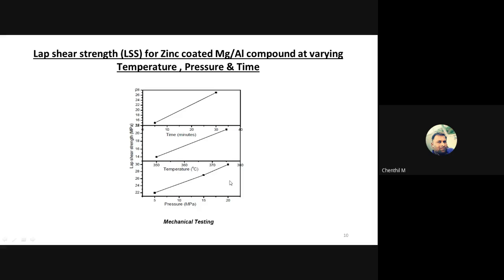The lap shear strength was found to increase with pressure from 5 megapascal, and it reached about 22 megapascal. Whereas for a pressure of 20 megapascal, it was about 30 megapascal. With respect to this, the temperature was maintained at 375 degrees Celsius, and the time duration was 30 minutes. This was the temperature and the pressure maintained with respect to the result under the mechanical testing.